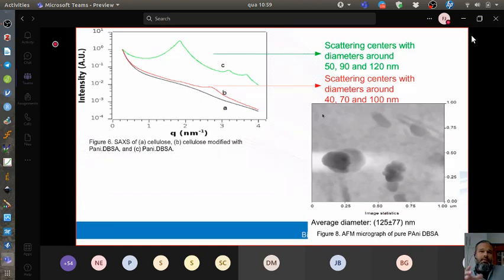As we can see, the largest one in average is around 110 nanometers. And it's very nice because when we compare the results from SAXS with the results obtained from AFM, we can prove that statistically the particles we perceived in AFM possess the same diameter of the particles observed using the small angle X-ray scattering.